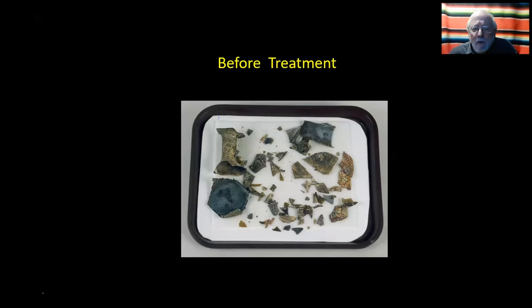Well, there are many ways of joining fragments, especially glass. One of the common ways of using an epoxy was to tape the glass together first and then wick it in using the epoxy, because the epoxy would take hours and hours to set, so you had lots of time to drip it along the break edges. It's very messy, it's a lot of cleanup, but it does work.